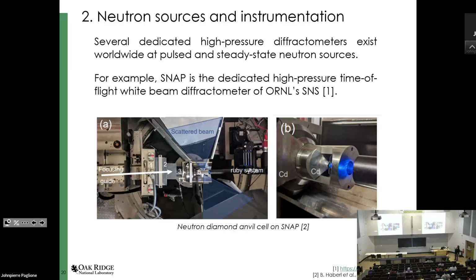So here is an example of the SNAP beamline, our high-pressure diffractometer at the SNS, the Spallation Neutron Source, where this was me standing on top of the instrument looking down. So the beam comes out of the wall here, and then it hits the pressure cell here and scatters in both directions. So here you see a diamond anvil cell that is on the beamline. One key advantage there is that we can actually walk up to the beamline because we always add a little bit of cadmium, our preferred shielding material, here or there to improve any background features.